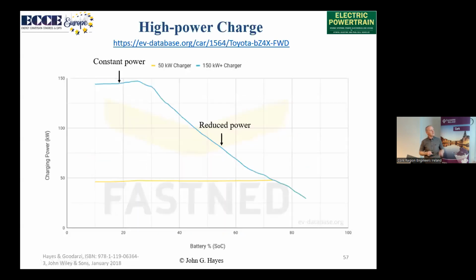We see this here. This is downloaded on the Toyota BZ4 on a high power charger, again from the EV database. They were pumping in about 140 kilowatts. They were able to do that till about 30% state of charge, and then they linearly reduced it to about 85% state of charge. And then they're probably heading down, and eventually we will only be able to put low kilowatts in to take us up to the final 100% state of charge.